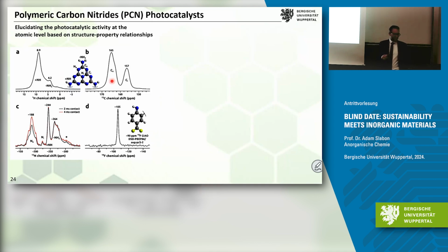These are many spectra, I'll just show you my favorite peak. It's this one, the graphitic nitrogen, and we collected this without any isotope labeling. The thing is, the abundance of nitrogen-15 is only 0.4%. So usually you have to do labeling, but we found out that if you take a very big rotor and insert 0.7 grams of material, you can get such a nice spectrum after 4 hours.